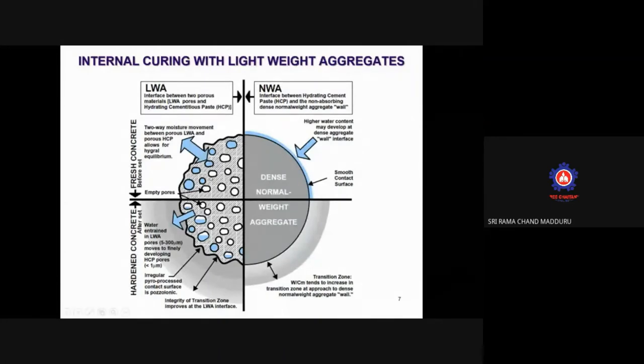You can see here, the left side image shows lightweight aggregate, whereas the right side image shows normal weight aggregates. The top picture is the fresh concrete, and the bottom one is the hardened concrete. So, before set, after set. If you see the normal concrete, when natural normal aggregates are used with high water content, a layer of water forms on top of the aggregate, leading to higher water content. This is the zone where the interfacial transition zone is. So the accumulation of a higher amount of water is making a poor interfacial transition zone.